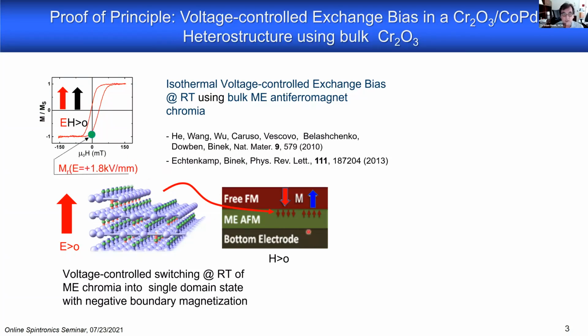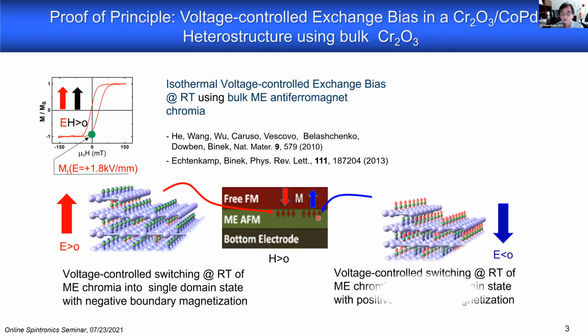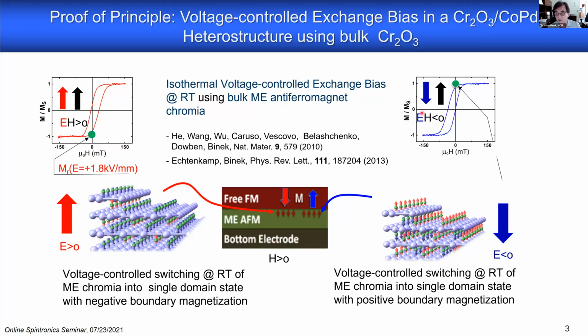Now we can turn it around. We can change the orientation of the electric field. We invert the boundary magnetization, and by doing so, we change the sign of the exchange bias field. So the product here of the applied fields is negative. The exchange bias field is also negative. These are actual measurement results we obtained in such a system, but as I said before, this was just a proof of principle in the sense that the antiferromagnet was a bulk single crystal. And then it took us quite some time, us and other groups in Japan, in particular Tohoku and Osaka, to bring this effect into an all-thin film geometry. I will talk about this in a second.